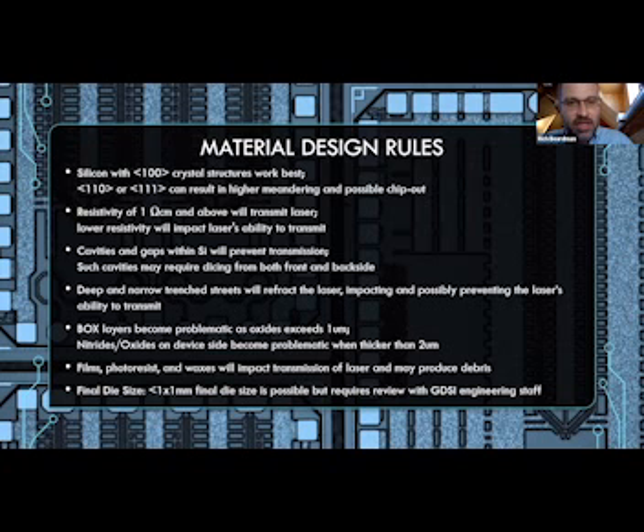Another thing that's key as far as material design rules go is the crystal structure. We typically prefer, or I should say the laser prefers, silicon with a 100 crystal structure. And the reason for that is if you go off axis on the silicon, you'll see not a beautiful clean separation in the center of the street, but almost like a lightning bolt. It's separating on the plane of the wafer itself.